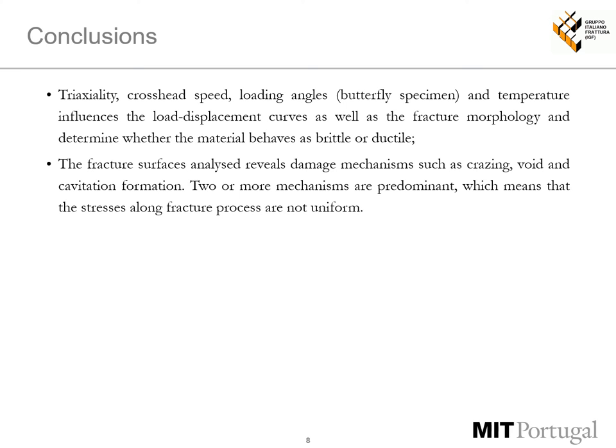Conclusions: Triaxiality, cross-head speed, loading angles, and temperature influence the load-displacement curves as well as the fracture morphology, and determine whether the material behaves as brittle or ductile. The fracture surface analysis reveals damage mechanisms such as crazing, voids, and cavitation formation. Two or more mechanisms are predominant, which means that the stress along the fracture process is not uniform.